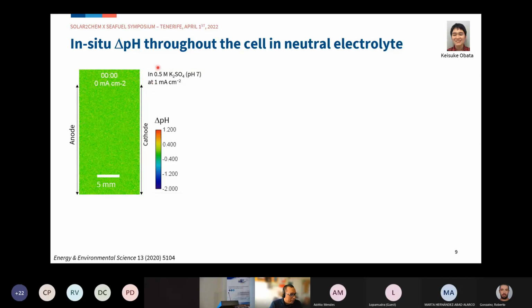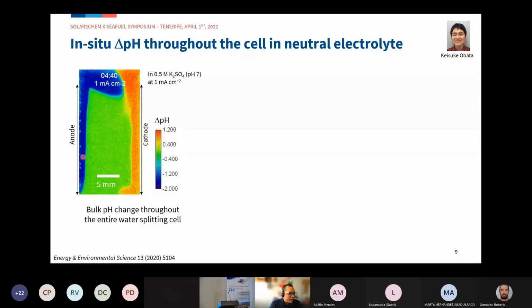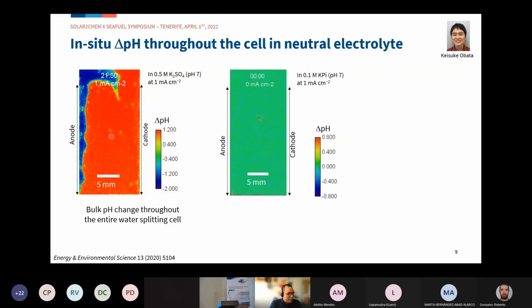First we look at an unbuffered electrolyte to make sure we clearly see the pH change. The color map here shows the change in delta pH. At the anode side, the electrolyte becomes more acidified, whereas at the cathode side it becomes more alkaline. The pH change is so severe that even away from the electrode, we see a really big pH change.